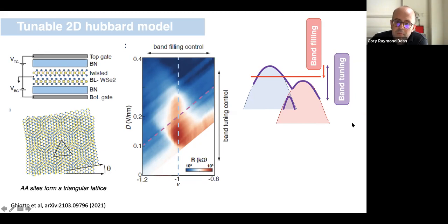So we have these gates top and bottom. And for a fixed twist angle, we can, as I just argued, tune this bandwidth by just applying a transverse field. But at the same time, we can also tune the filling. So basically by asymmetrically coupling to these gates, we can tune the bandwidth. By symmetrically coupling these gates, we can tune the filling, and we can independently control those two parameters. So this is actually quite interesting.